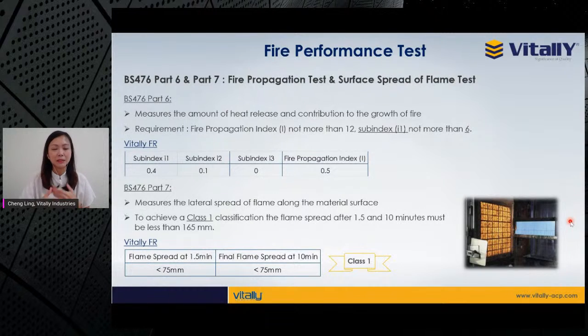So I'll briefly explain the four fire performance tests that we have done. The first one is BS 476 Part 6. This test indicates the performance of a material in the early stage of a fire, and the result is a fire propagation index. The lower the fire propagation index, the better the resistance of a material against fire growth. For this test, we achieved 0.5 for the fire propagation index, and for the sub-index, our result is less than 6.